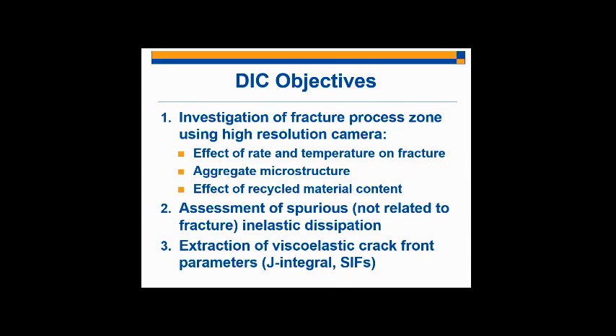And so what kind of things can we do with this DIC that we couldn't do with just the raw data that we extract from the test? We can look at the effect of rate and temperature on fracture. We can quantify the effect of the aggregate microstructure on fracture energy results or displacement results. We can look at the effect of recycled material content being added to the mixture in a way that we wouldn't be able to see with just the raw data extracted from the test.